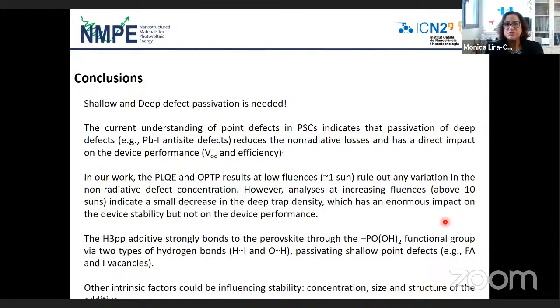So my message is that we have to passivate. We have to look not only to passivate deep defects to increase efficiency and voltage. We also have to take into account shallow passivation, shallow defect passivation. And we have to keep, even though we're able to increase efficiency and stability, analyzing shallow defects to see if we're also passivating our solar cells that way.